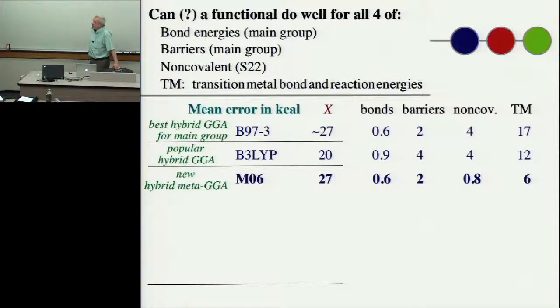But our M06-L does. But it's not the kind of local that most people use, because it has the kinetic energy density. But in the hydrogen bond, it definitely depends on the pressure, on how much you squeeze the hydrogen bond. So suddenly the local functionals start working when the hydrogen bond is short.